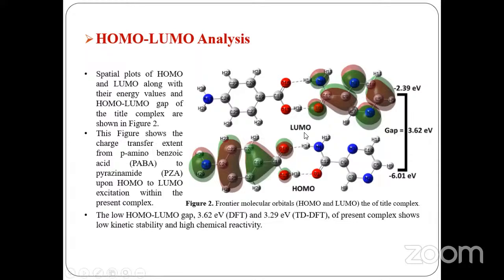And the HOMO-LUMO gap is found to be 3.62 electron volt from the DFT, which is close to the 3.29 electron volt obtained from the TD-DFT calculation. So this result shows the compound has low kinetic stability and high chemical reactivity.